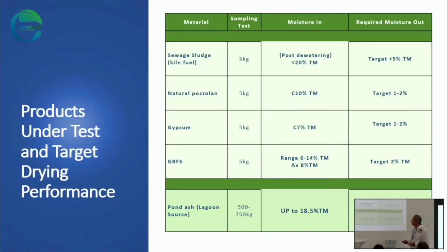These are some of the results. Now, due to some logistics snags, we haven't done as much of the production samples as we hoped to do, but we have been able to do all of the initial evaluation. So when I say it's a well-chosen selection, GBFS at the bottom of the upper block is at the easy end of things to dry. It's very free-flowing material. All the moisture is on the surface. It's very well suited to what we call kinetic drying, to drying it in an airflow.